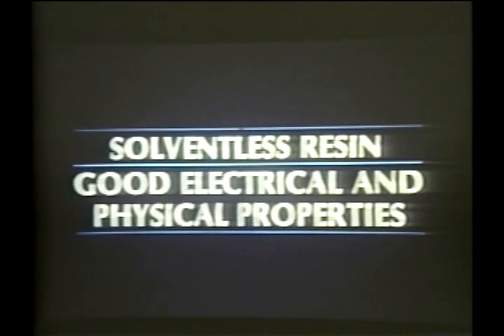The second is to use a resin-rich insulating tape or wrapper that has been pre-impregnated with a resin, the B-staged approach. And the third is to use vacuum pressure impregnation to force the resin into the composite to impregnate it with a resin after it has been applied. Now, all of these processes will produce good windings, and they all have advantages as well as disadvantages. But the key is to use a good solventless resin that has good electrical and physical properties. How we get that resin into the insulation system is less important than the quality of the resin itself.